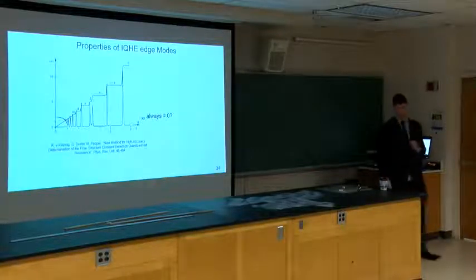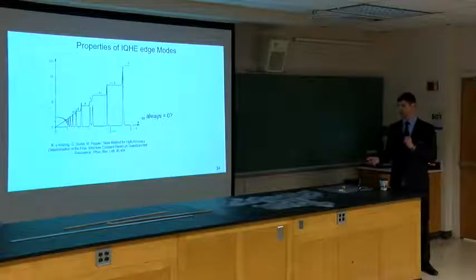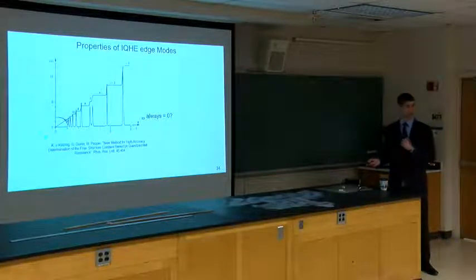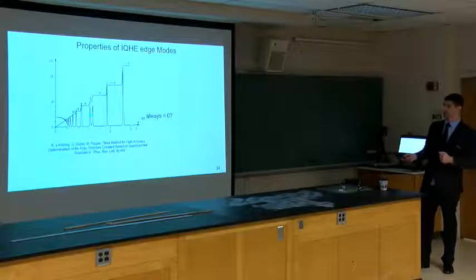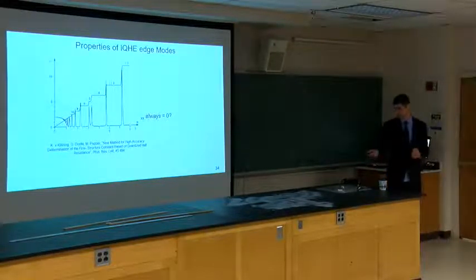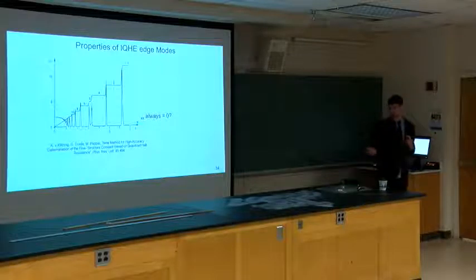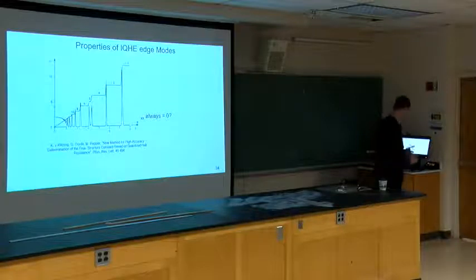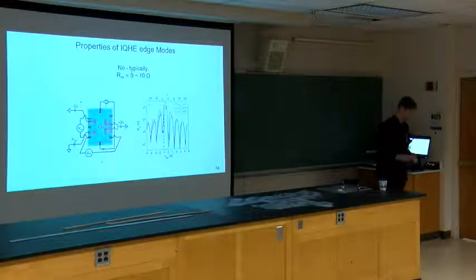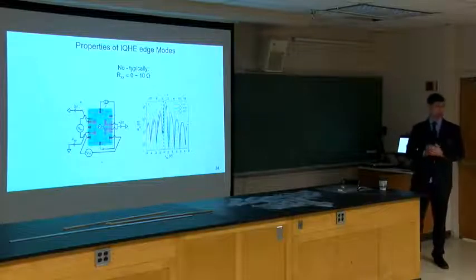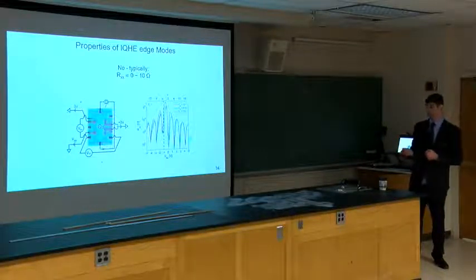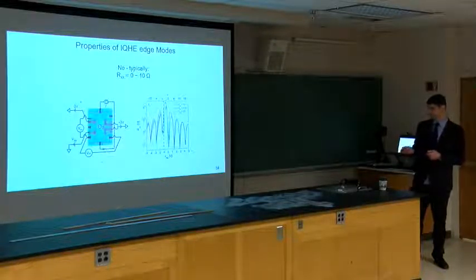So if we look at a few more properties before I actually cover the work, this value here looks like 0, right? I could believe that. And this is from von Klitzing's work. But is it always 0, Rxx? Is it actually dissipationless? I know this is theoretically what is predicted, but the reality is that no, it actually isn't. If you plot that previous plot, as I'm plotting some of my data from a Hall bar, we're plotting the longitudinal resistance: pass a current, and measure resistance along 2 probes.